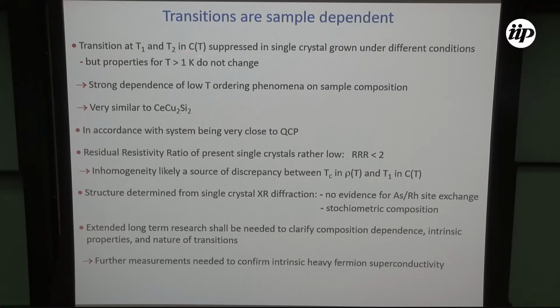Because what we also found, we tried a different type of crystal growth, and we found that the transition at T1 and T2 in the specific heat can be suppressed in single crystals if one changes the growth condition. So we have now learned how to prepare single crystals which show a transition and to prepare single crystals which do not show the transition. So in this sense, it's reproducible. The interesting point is that above 1 Kelvin, there is no change in the properties. So the characteristic energies are essentially the same. And this means that only the low temperature ordering phenomena depend strongly on sample composition.